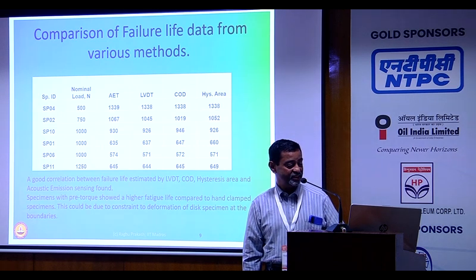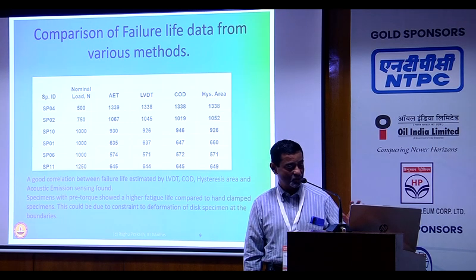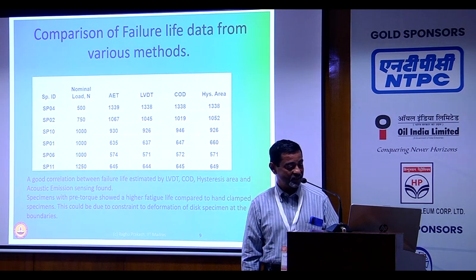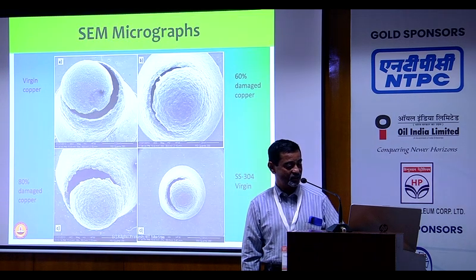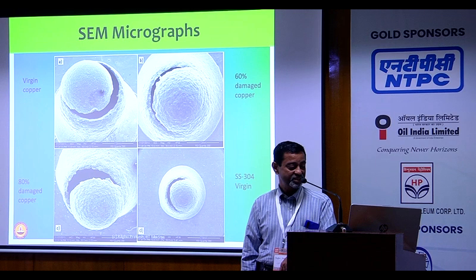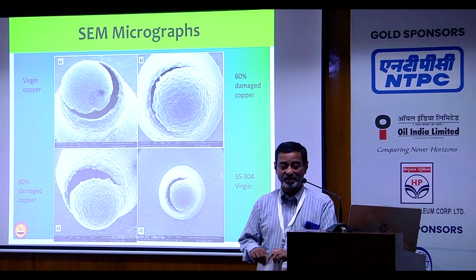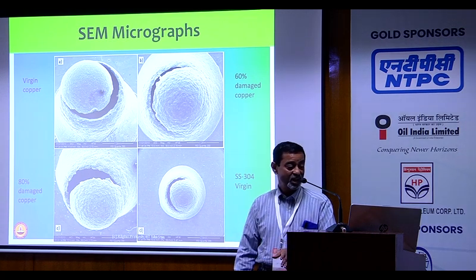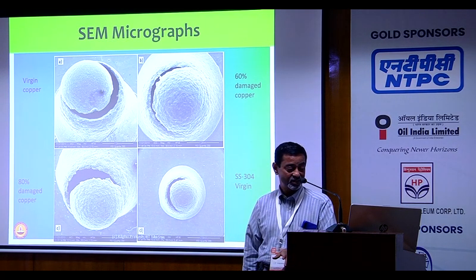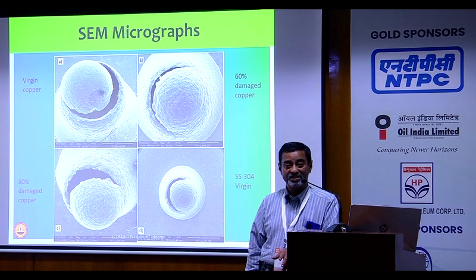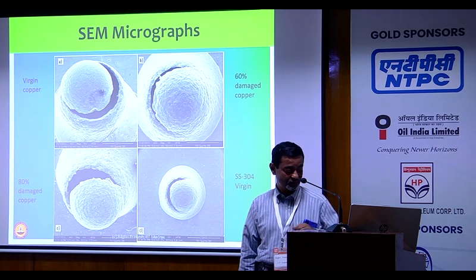And when we did the multi-sensor technique, we tried to correlate the data of fatigue life from various test methods, and the table you can see over here shows that there is a good comparison. We have tried the acoustic emission technique. We have also used the hysteresis area for measurement of the energy that is stored during fatigue cycling. So this is one of those tables. And you can see here, when we took a small scoop sample and did a cyclic small punch test, I'm able to get different micrographs, which also suggest where the crack is initiating, how it is growing, all that kind of detail.